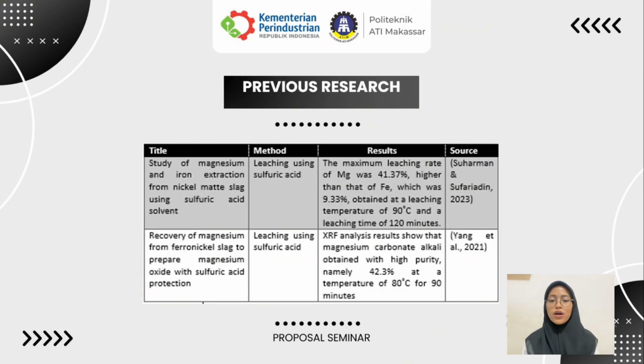Furthermore, the first previous study that I used as a reference was titled Study of Magnesium and Iron Extraction from Nickel Matte Slag using sulfuric acid solvent, which used the leaching method. The results obtained were a maximum magnesium extraction rate of 41.37%, which was higher than iron at 9.33%, achieved at a leaching temperature of 90 degrees Celsius and a leaching time of 120 minutes.